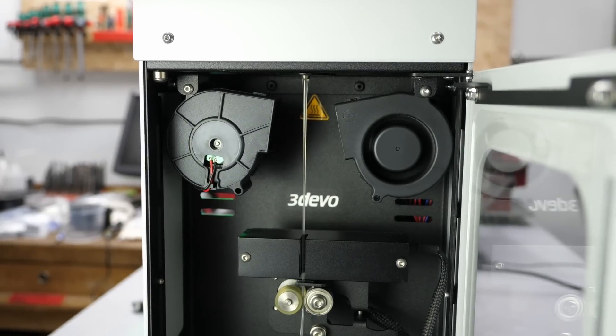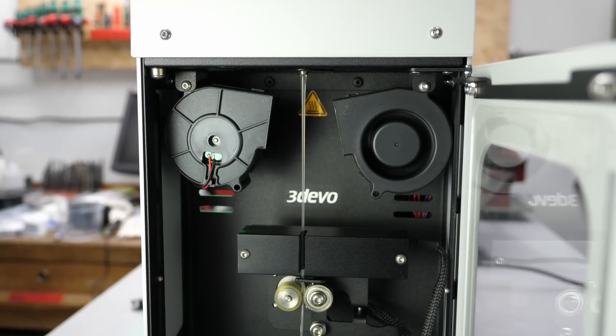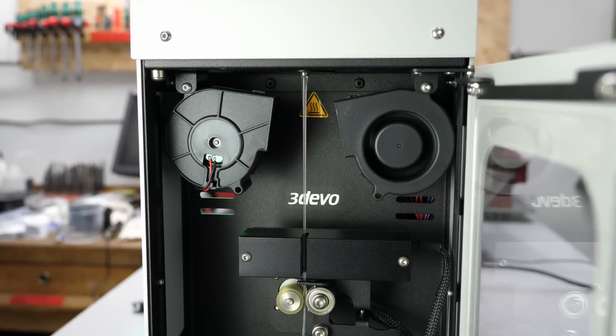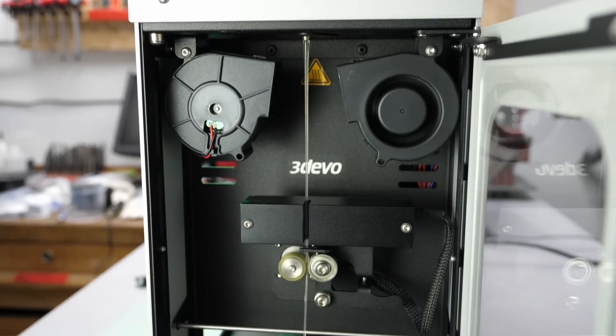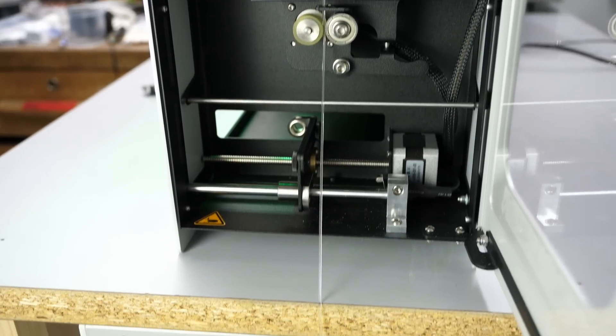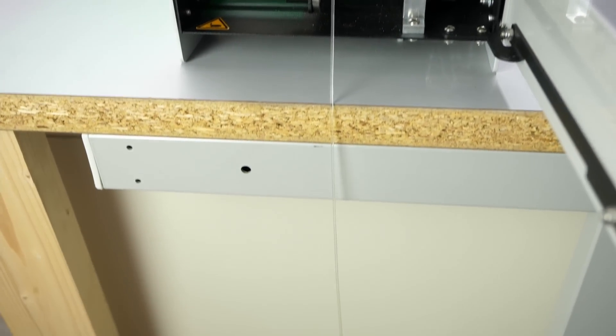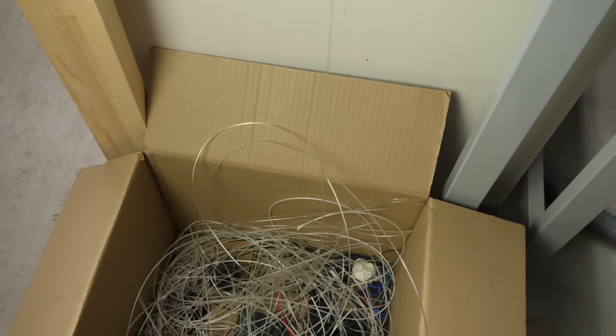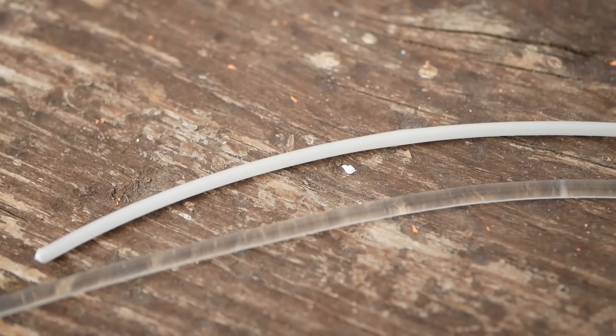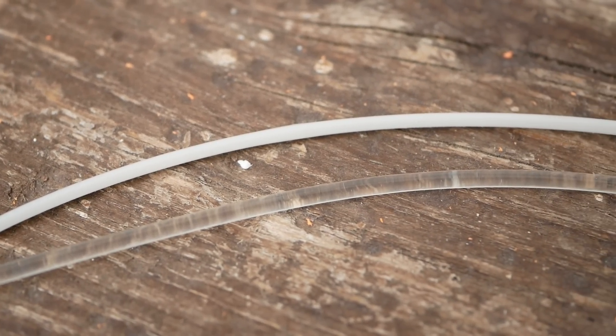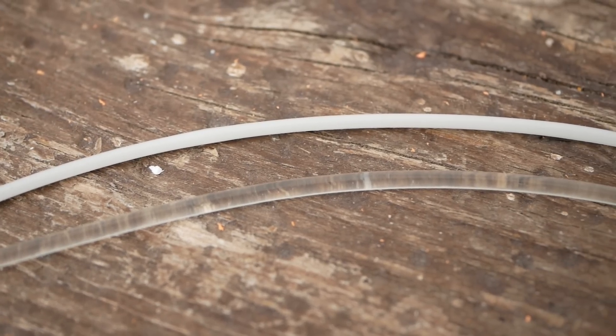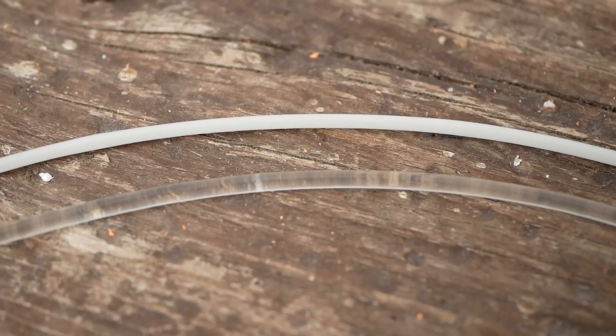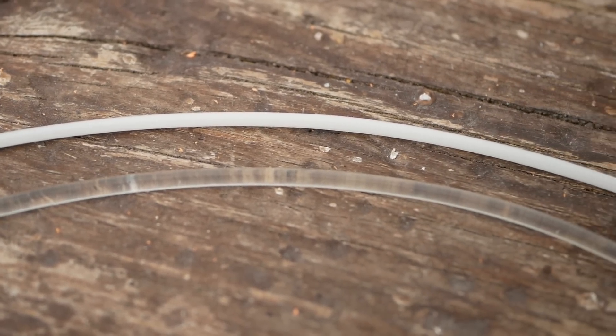Since I had another material in the extruder before adding the PLA, I'm first purging that out and during this waiting time, the temperatures within the whole machine stabilize to give us a more precise filament diameter in the end. Once PLA is coming out of the nozzle and the diameter stabilized, we can continue with spooling. You can spot when the material is coming out because the HDPE that was in the machine before crystallizes into white filament, whereas PLA remains mostly transparent.